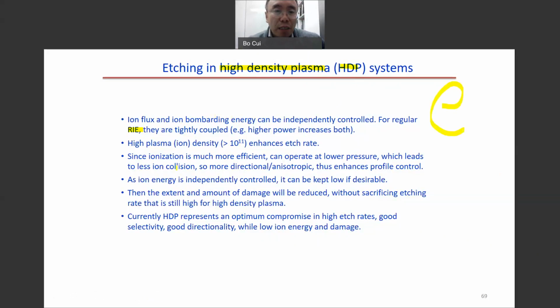Because ionization is much more efficient, we can work at a low pressure. When we have lower pressure, there will be less collision, more directional etching. And also the ion energy can be controlled. For example, sometimes we want low ion energy. When we have a low ion energy, the damage to the substrate will be smaller, and also the selectivity will be higher. Etching rate selectivity.